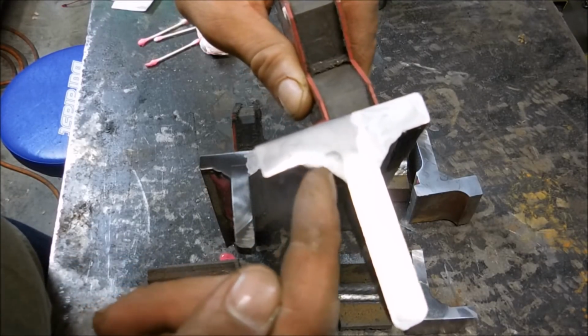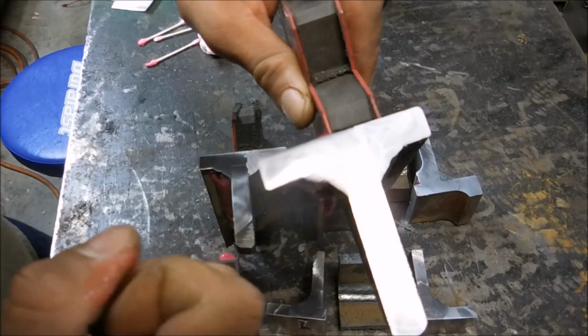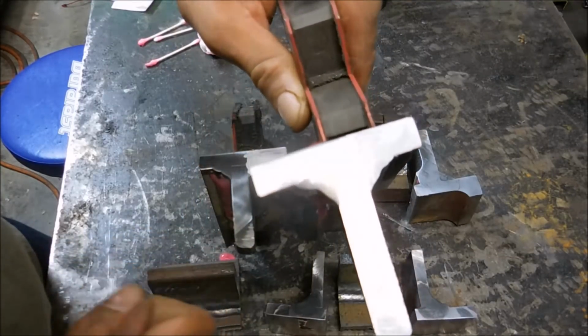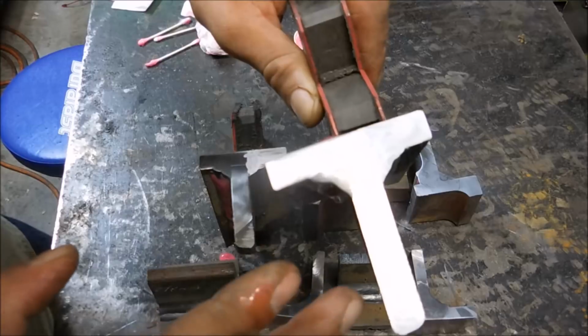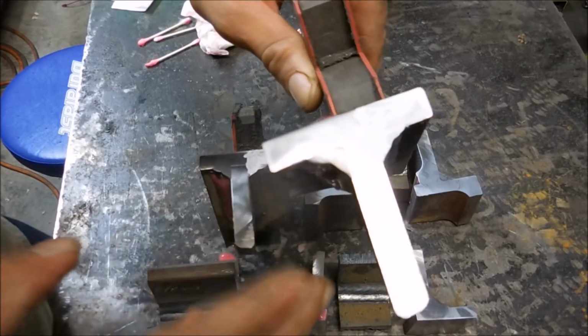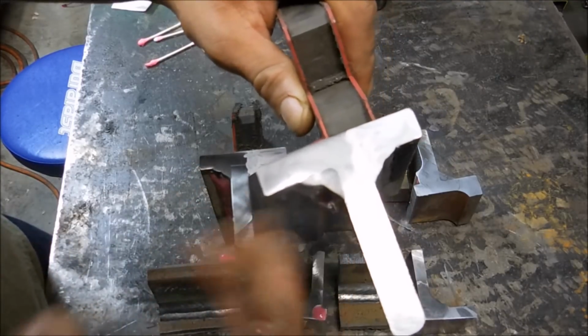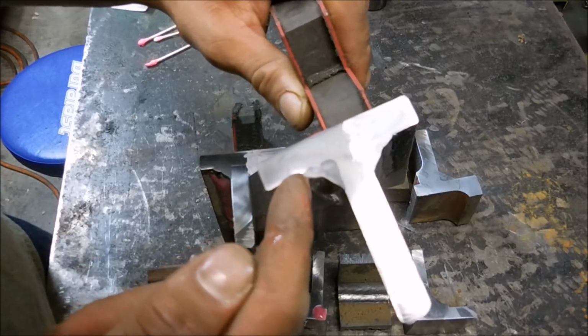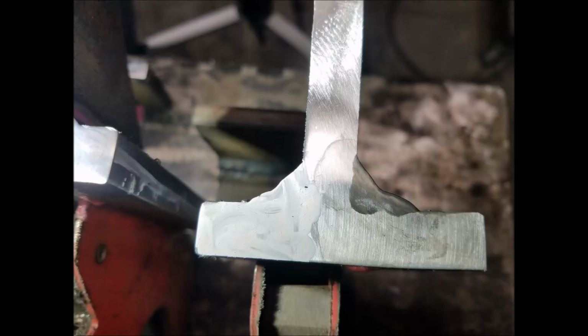There you go. There's a valley that runs down there, and that's not proper stacking of beads, right? And that's what I got from welding directly over slag. You can't really see the toe of this second pass when you're putting the third one in there. Now here's a close-up of the first coupon, 3 passes, no cleaning at all.